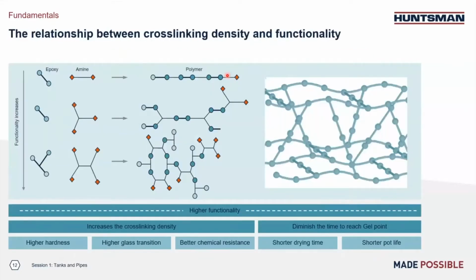And this slide tells us why high functionality epoxy resin is important. So if we're using just a linear system, such as two functional epoxy with two functional amine, we have this kind of very linear structure. On the other side, if we're using three functional epoxy resin and four functional amine, so both high functionality system, instantly we have this high crosslink network. So it's very similar to this image on the right side.